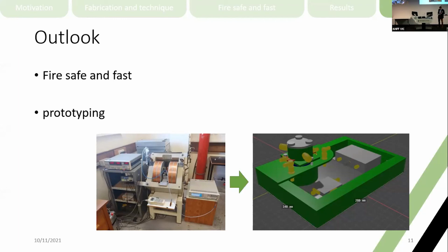Great, thanks, Thomas. Savanka is asking, how did you calculate the hydrogen diffusion speed? That was actually not us, that is from different research. It's a very interesting research. They used an optical method, they did microscopy on it and had a transparent window over a cobalt palladium alloy so that the hydrogen was only absorbed on one end of the cobalt palladium film, and they could look through that glass window how it progresses, and they calculated the diffusion speed from the hydrogen front, basically.